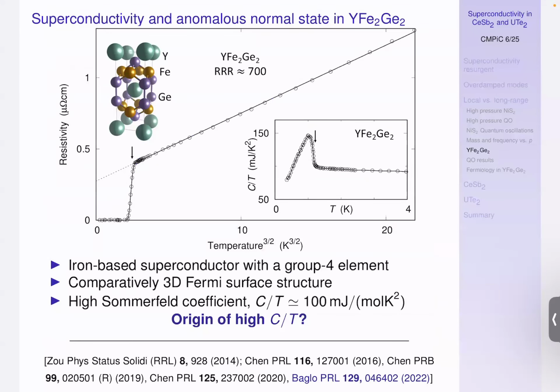So, the point with yttrium iron 2 germanium 2 is it's one of the few iron-based superconductors that don't have a pnictide or chalcogenide element to make up the structure. It's a germanide. And it has a fairly low TC of about 2 Kelvin in resistivity, 1.2 Kelvin in heat capacity. And it has a very high Sommerfeld ratio, about 100 millijoules per mole Kelvin squared.